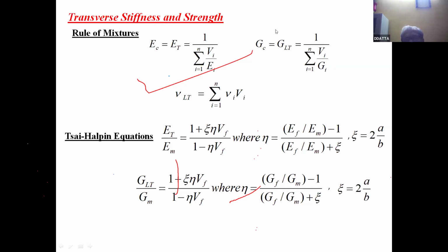But these predictions of transverse properties by the rule of mixtures do not seem to be good if we do experiments and look at the experimental results. That is why Tsai and Halpin, these two people who are very famous in the composite industry, derived these semi-empirical relationships, by which we can calculate E_T and G_LT. Some part is experimental, some part is theoretical. They did some curve fitting and then obtained this sort of equation. But these do well, and their results match well with the experimental observations.